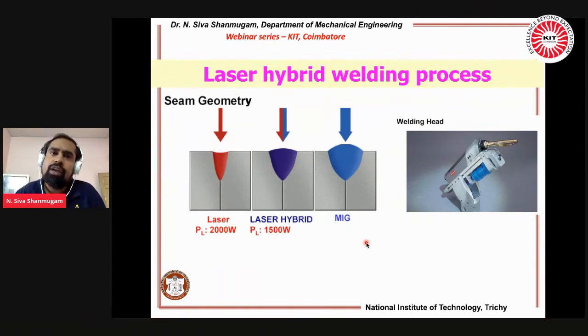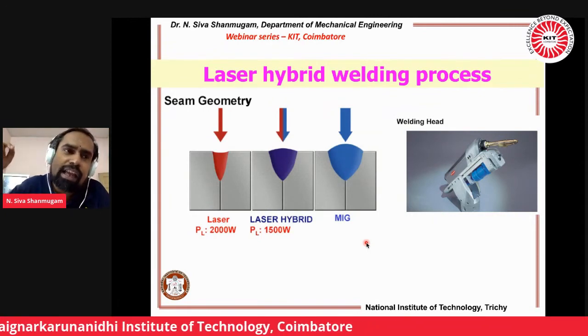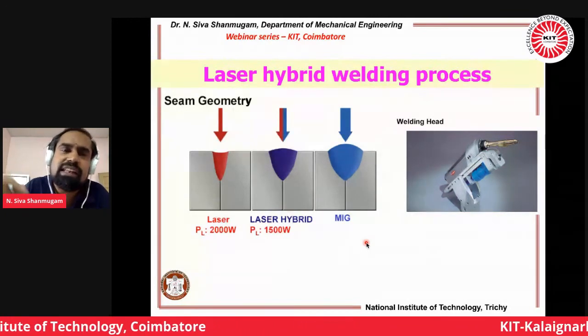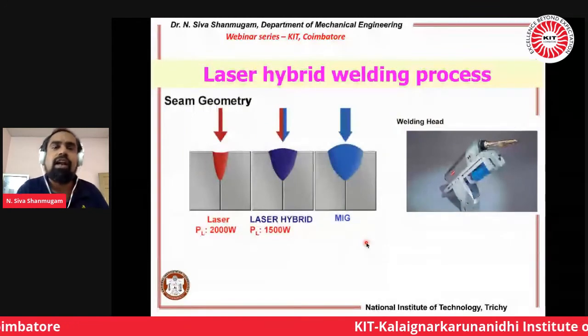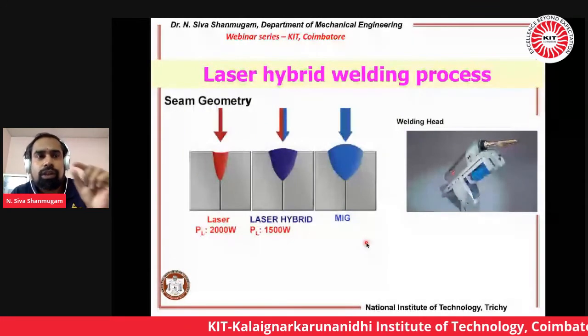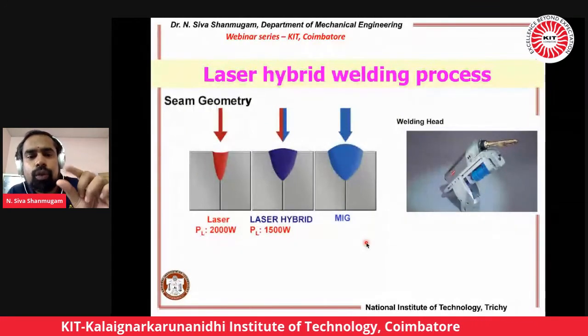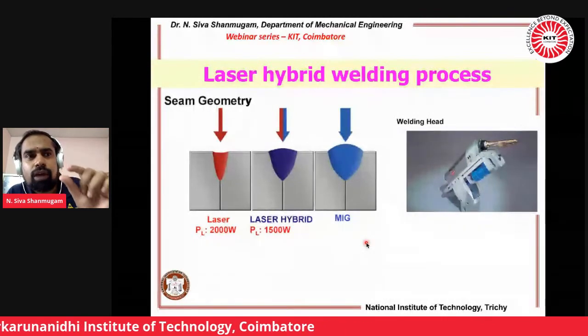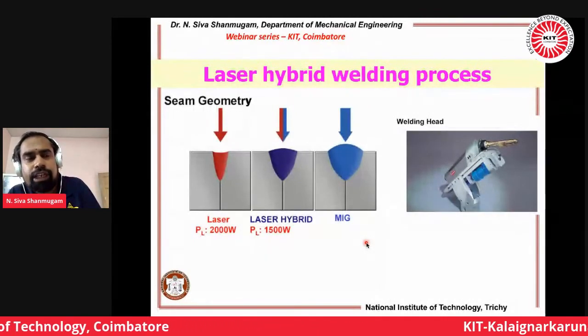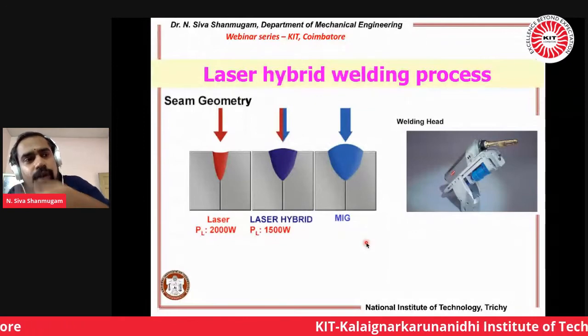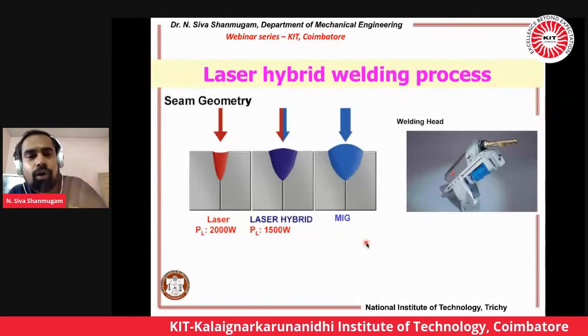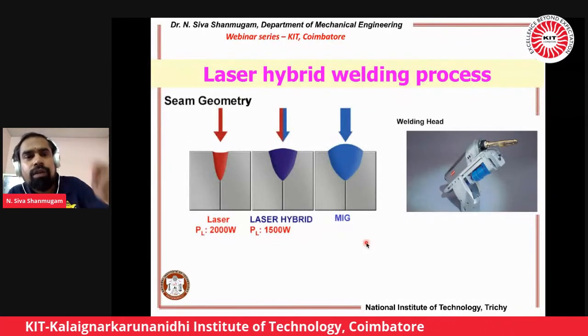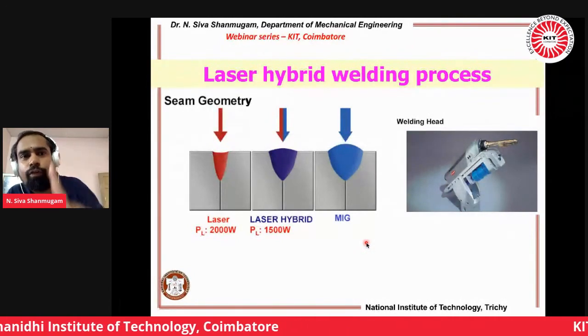That's why you are getting a very high deposition, very high intensity beam is piercing the material. So that's why you have to properly use the beam power. If you use the 1000, it will penetrate. If you are using it on the foils now, it will burn through the entire material. You are getting a hole. Instead of fusion, you will get a hole with the diameter of 1 mm.